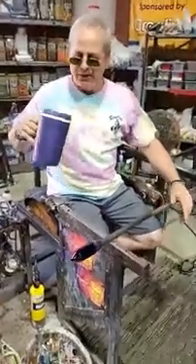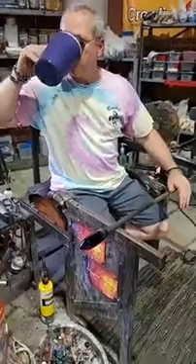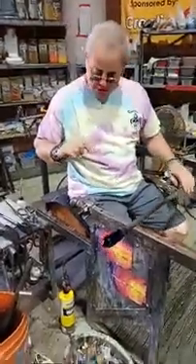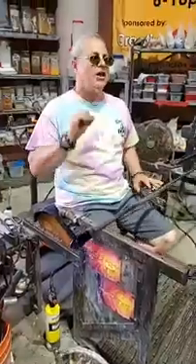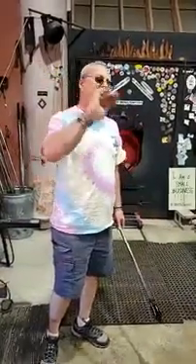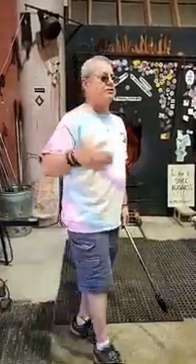Yeah, I'm allowed. Absolutely. So Curly wants to know, what's the hardest color to use? Reds. Period. Exclamation point. Reds are really hard because they burn out easily, meaning they go to brown real easily, and they're harder to blow. Some colors are softer, like white is real soft. Red is really hard, so if you don't have it evenly on the piece, it'll blow out crooked. So reds are definitely the hardest to work with. Another layer on top.